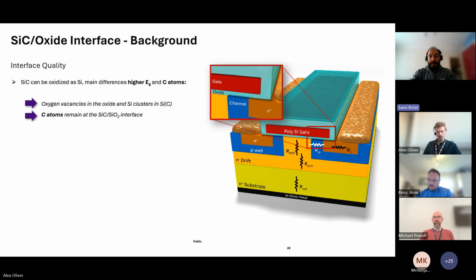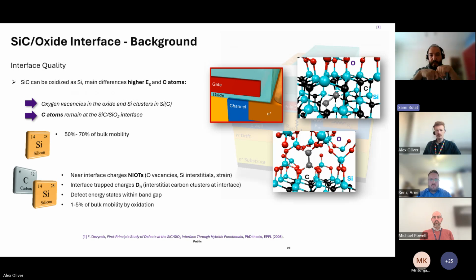So silicon carbide is a really good material in the sense that we can easily grow the thermal oxide on top of it. This is similar to silicon. That's why among the wide bandgap materials, it also stood out as an industrially adopted choice for power electronics. But the main difference is we have a wider bandgap that limits the reliable operation area with the silicon dioxide used as dielectric, and we have the presence of carbon atoms. For silicon, we have the saying that the silicon to silicon dioxide interface is a God-given interface, and for silicon carbide to silicon dioxide, we can use an analogy that it's a devil-given interface. Because for this one, we are suffering from all kinds of defects at the interface that are creating these near interface oxide traps.